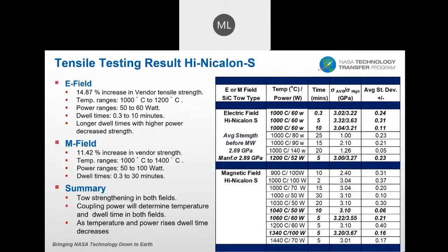And now in the magnetic field, what we see is about a 12% increase over vendor strength. Temperature ranges from 1000 degrees C to 1400 degrees C. Power ranges from 50 to 100 watts. Dwell times from 20 seconds to 30 minutes.